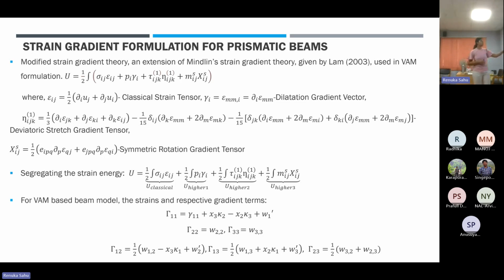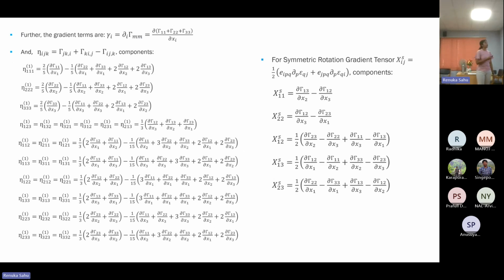We segregated the strain energy in terms of classical higher-first case, which corresponds to the dilatation gradient vector; higher-second case, which corresponds to the deviatoric stretch tensor; and higher-third, which is the symmetric rotation tensor. We start with the classical strain terms, given here, and then move on to the higher gradient strain terms, for which we obtained these particular expressions using the definitions of these gradient strain tensors.